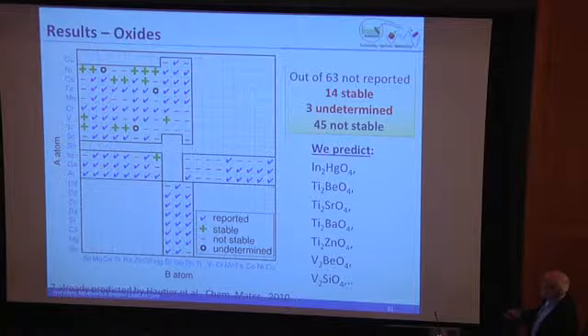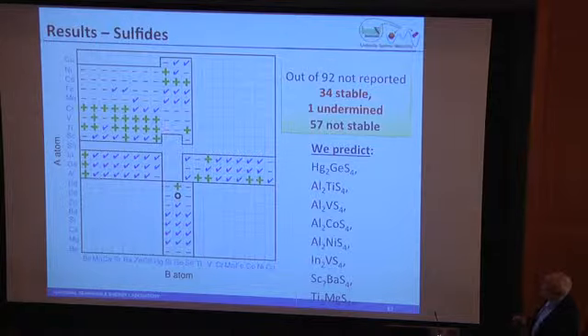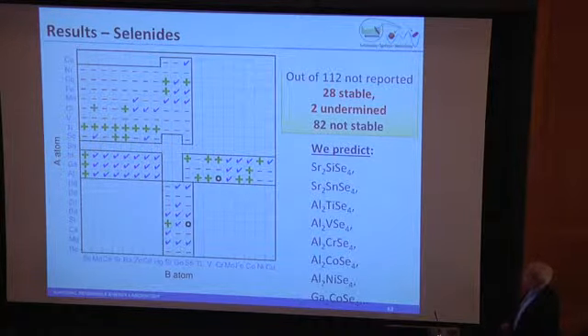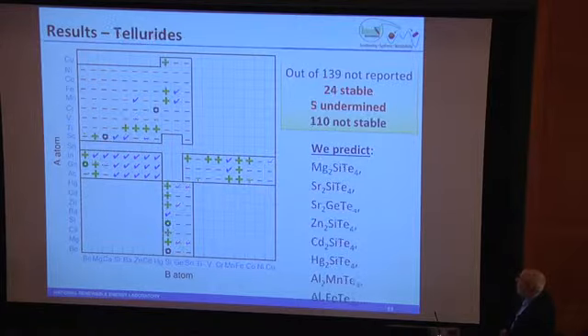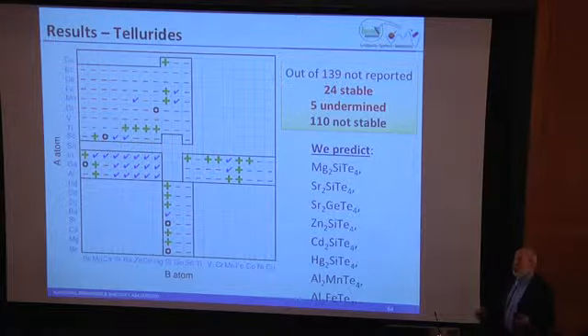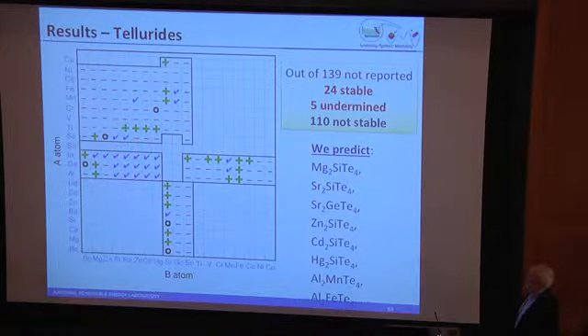If you look more, you can see that there are ones that we expect to be stable that haven't been made. There's ones that we don't think are going to be stable, and there's ones that we really don't know. Probably most of the ones that we don't know means that you're not going to be able to get to them. If you look at sulfides, the number of the pluses is actually much larger. And if you look at the selenides, again, there's a large range of materials. Now, this is interesting because a lot of these materials are potentially solar cell absorbers. They're active optoelectronic materials. They're all interesting.